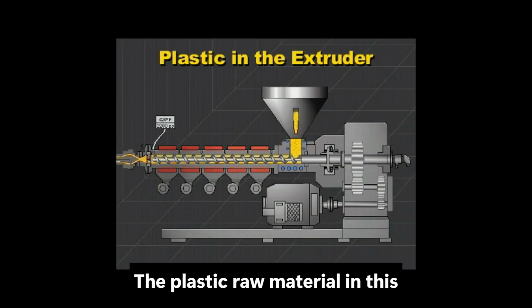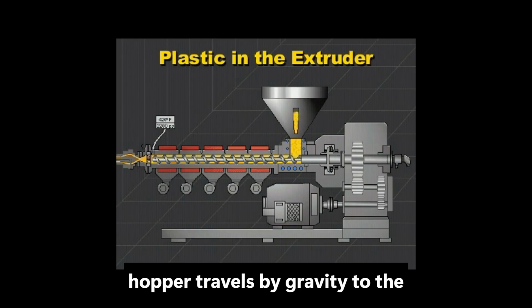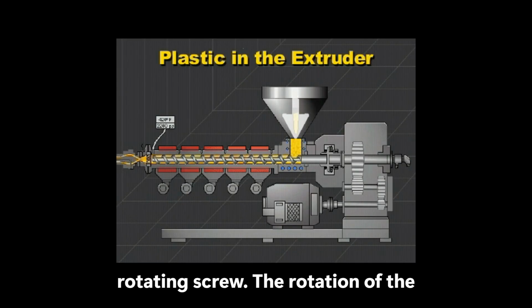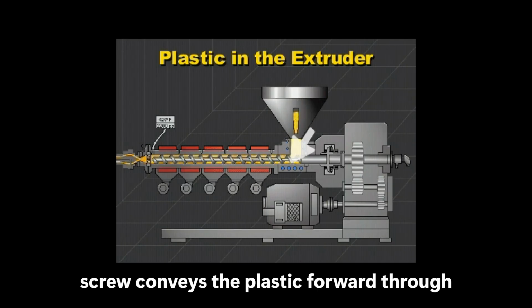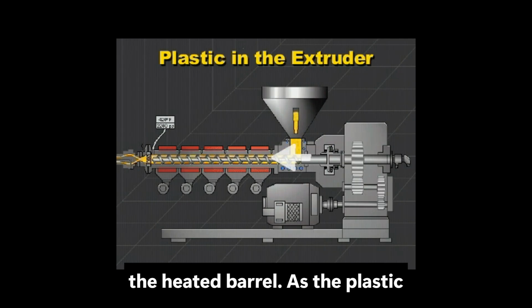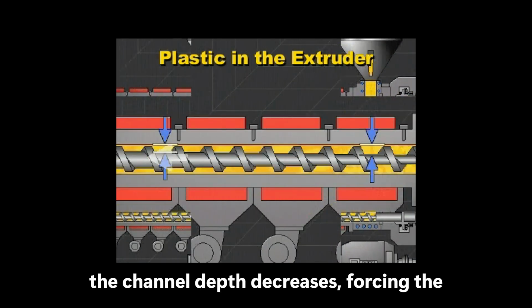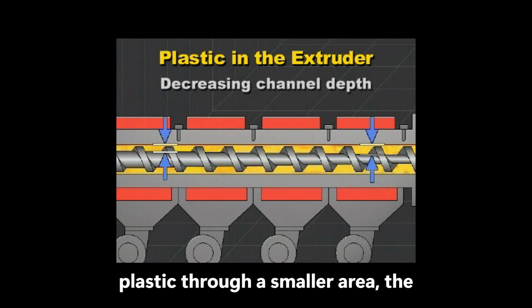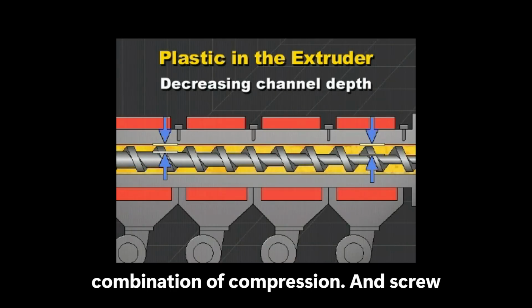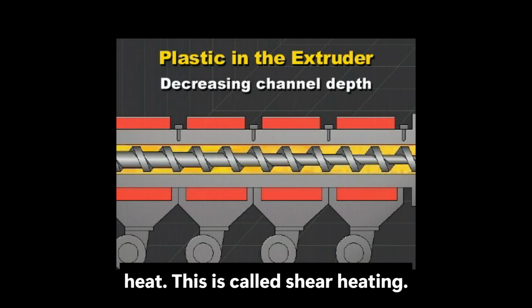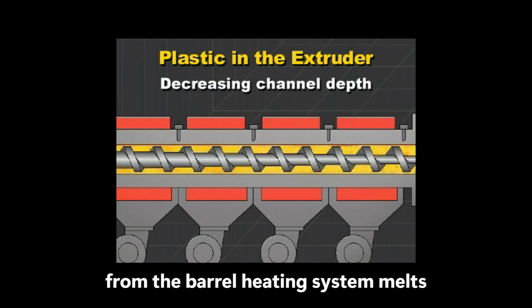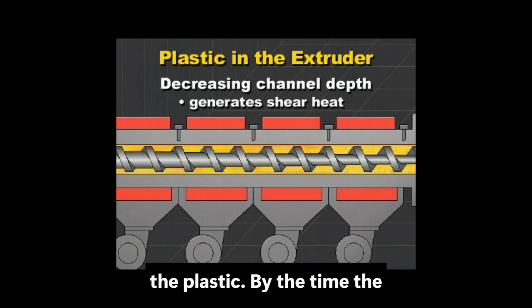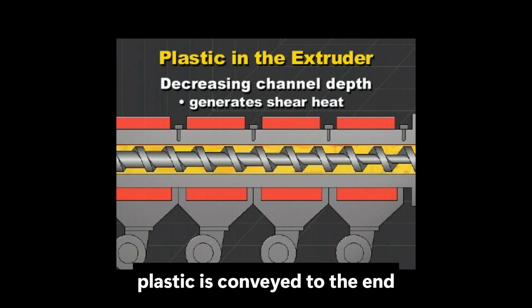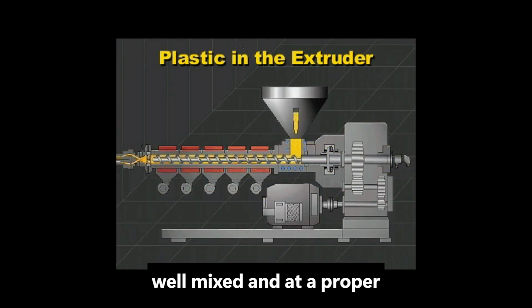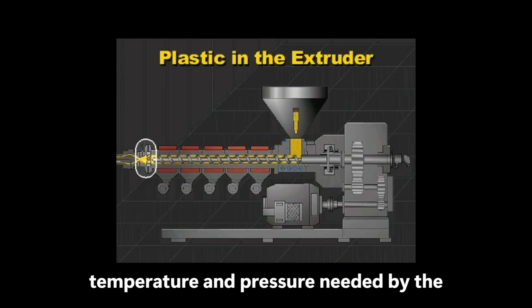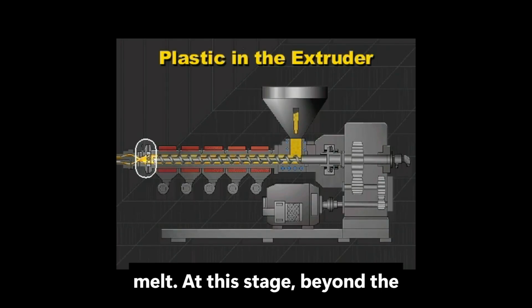The plastic raw material in this hopper travels by gravity to the feed throat and drops onto the rotating screw. The rotation of the screw conveys the plastic forward through the heated barrel. As the plastic is conveyed forward along the screw, the channel depth decreases, forcing the plastic through a smaller area. The combination of compression and screw rotation causes friction, which generates heat. This is called shear heating. This heat, along with the heat from the barrel heating system, melts the plastic. By the time the plastic is conveyed to the end of the screw, it should be well mixed and at a proper temperature and pressure needed by the die. The plastic is called a melt at this stage.